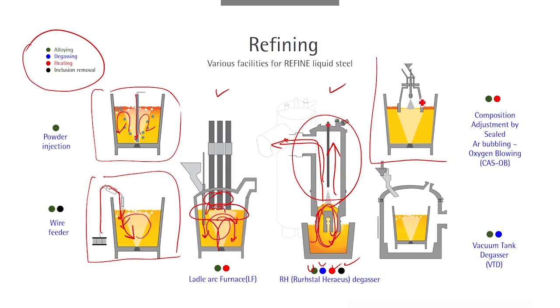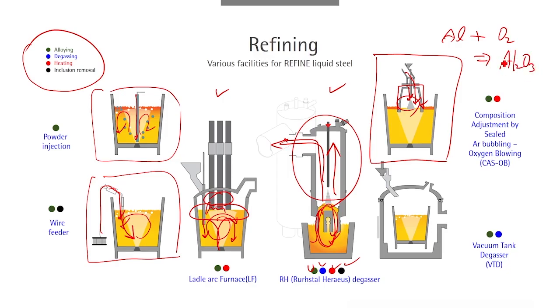On the right-hand side is a facility called composition adjustment by sealed argon bubbling and oxygen blowing, simply called CAS-OB. It has a hopper where oxygen is blown and aluminum is added. Aluminum reacts with the oxygen gas, forming alumina with a lot of heat, making this another type of heating facility. Liquid steel is well agitated by argon gas so temperature is evenly distributed.